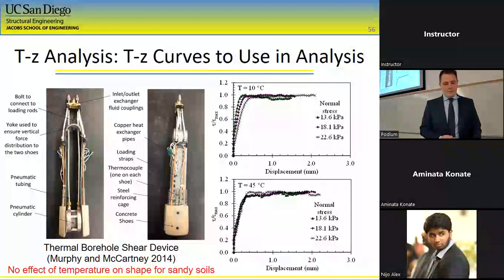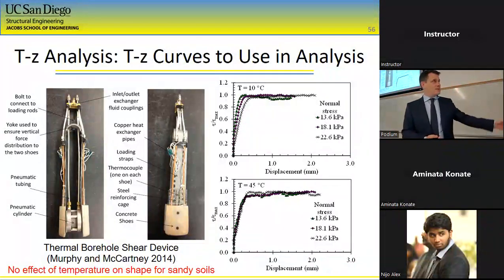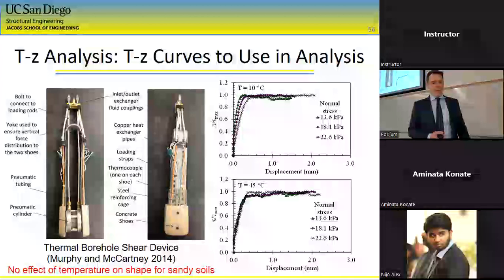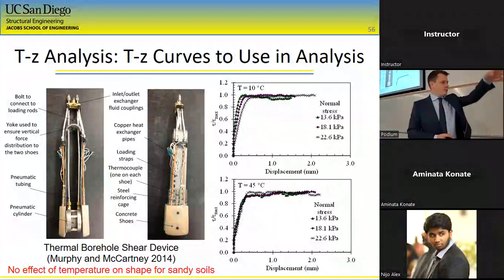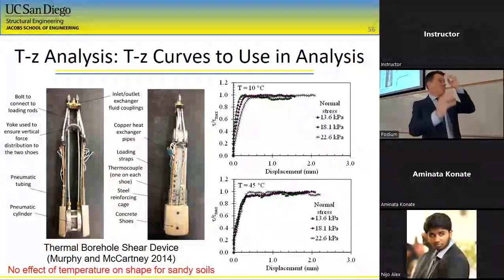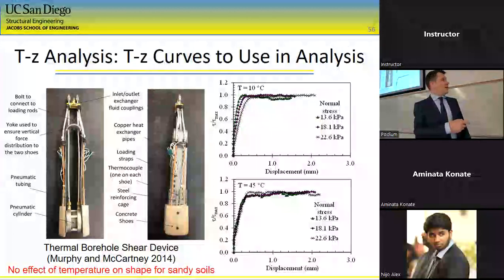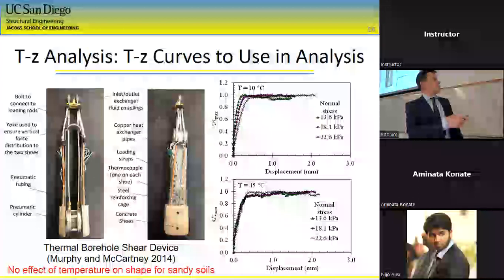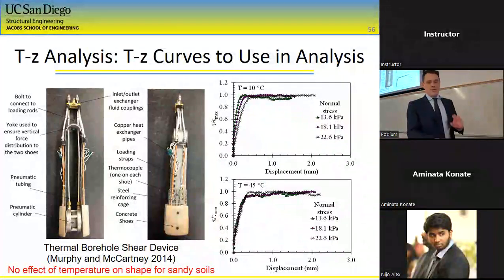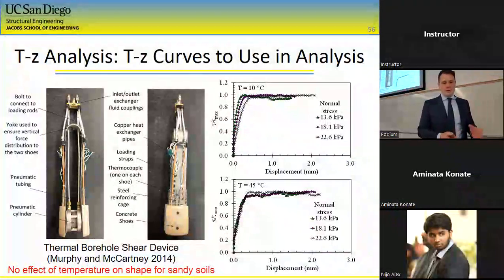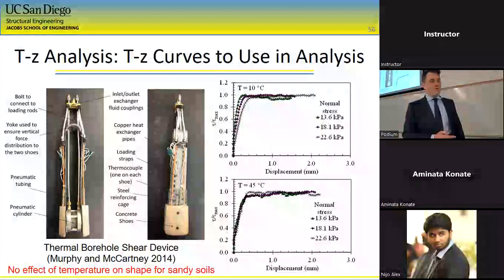Trying to simulate it, we want to measure this TZ curve. So the way we did this is we made a special device that we could put down a borehole, expand against the sides of the borehole, and then pull upwards. This is the Iowa State or the Handy borehole shear test, but we incorporated temperature changes. So we did temperature changes and found that temperature didn't have a major effect on the shape of the stress strain curve, which was good. We could do a simple analysis and use the same normalized stress strain curve at every depth.